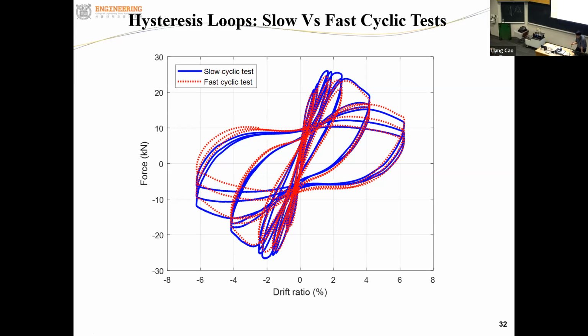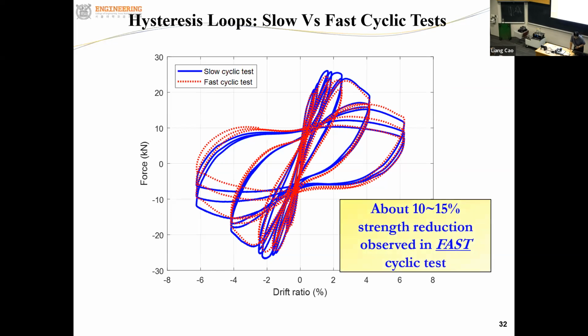Also, it depends on the details of the layout of the rebars. But for this selected column system, we observed this reduced strength after the real-time testing. So it's about a 10 to 15% strength reduction, which demonstrates the importance of real-time testing.